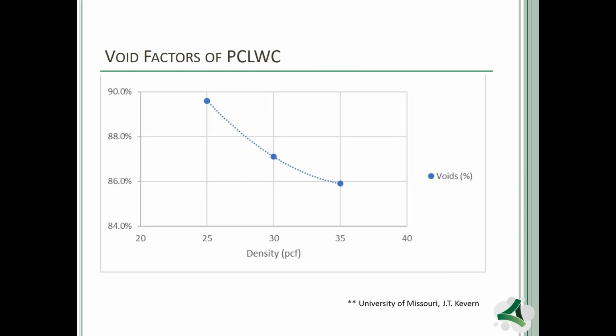The void structure within pervious cellular concrete is quite extreme, and was demonstrated by the University of Missouri at Kansas City. You will never fill 100% of those voids with water infiltration. I always suggest to people to consider 55% of the volume for water infiltration, but don't go above that, because you'll never fill up every void within the structure. So consider 55% of that volume can be utilized for water infiltration, which obviously helps with counteracting any buoyancy issues that you might encounter.